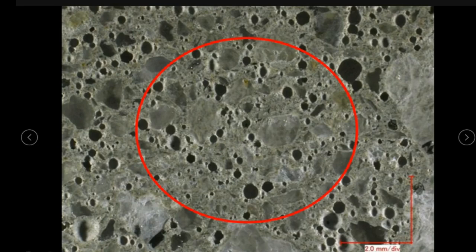But if your concrete has a very high water cement ratio, basically it will look similar to the lightweight concrete. Lightweight concrete actually is not a structural material, because we cannot use it to build the structural elements, the column, the beam, the slab, everything, because it cannot take load. The compressive strength is only about 8 to 12 megapascal, so normally it is used as partition, furniture, insulation, insulator wall and so on, but not as structural components like beams and slabs.